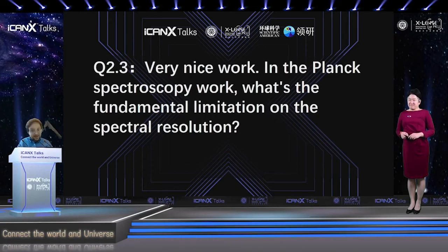However, just because there is no fundamental limitation doesn't mean that there is no limitation. In fact, there are very substantial limitations. This problem of inverting the spectrum to get a temperature versus depth is actually quite poorly conditioned. It's a very difficult problem. Essentially, you need very high accuracy and very good precision in your spectral measurement to get an accurate and precise temperature with high resolution, in both temperature and spatial resolution in depth. And what we've found is that even with our quite sophisticated calibration, we can't get much better spatial resolution right now than on the order of 100 microns in depth.